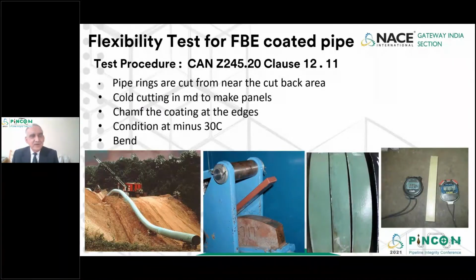Okay, let's see how the flexibility test is done. We mentioned three parameters, and one of them is flexibility. So as per the Canadian standard specification procedure, the FBE coated pipe needs to be cut into something like a 1 inch by 8 inch size panel. In the middle picture, you see a brown color panel, which is actually a piece of pipe. Before it is bent, it is kept in a freezer at minus 30 degrees Celsius for at least 1 hour so that the temperature is stabilized.